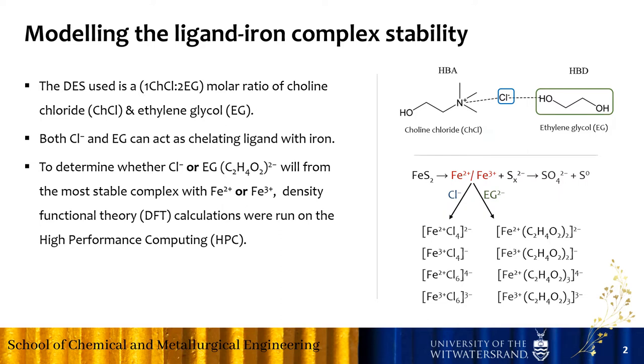The specific DES used in this work is a combination of choline chloride and ethylene glycol in a molar ratio of one to two. In this DES, there are two ligands — chloride and ethylene glycol — which can act as chelating ligands for iron and may complex with iron.